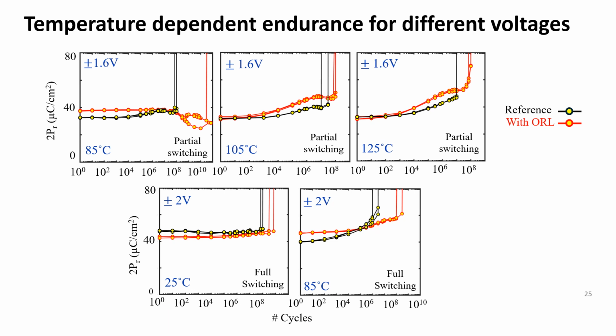Next, we measured the endurance at multiple voltages as well. For example, you can see the top panel is coming from the measurements done at 1.6 volt fatigue cycling, and the bottom panel is coming from the measurement done at 2 volt fatigue cycling at different temperatures. In all cases, you can see that the red curve, or the measurements done on the ORL device, has higher endurance compared to the reference device. And we have measured multiple devices for each voltage and each temperature.